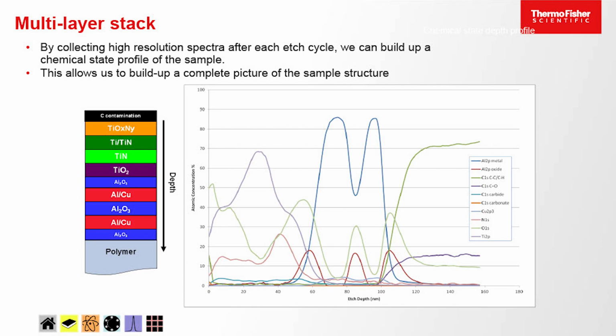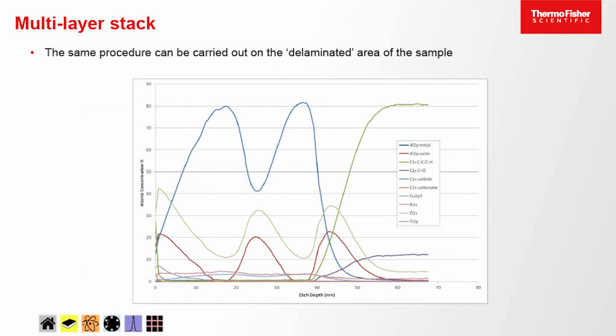So we can look at the delaminated area as well. This one is the actual real sample, and then if we look at the delaminated area, we can see that we don't get quite the same profile. And so we can see here by the layer that we're coming in at here, there's going to be a little bit of oxygen, this is the aluminium oxide, so it's one of the aluminium oxide layers where the coating is breaking down.